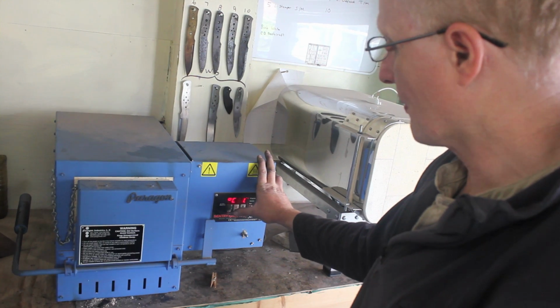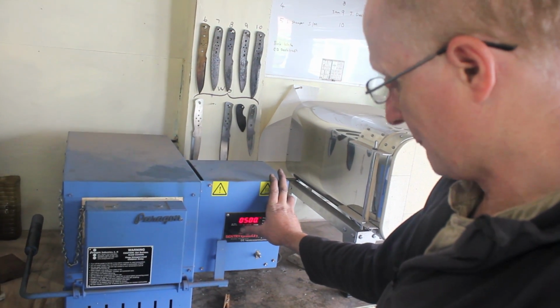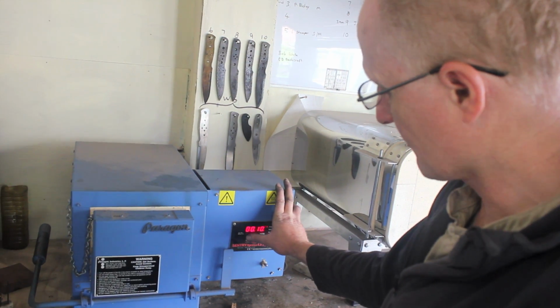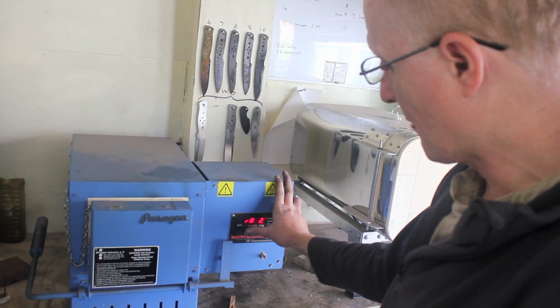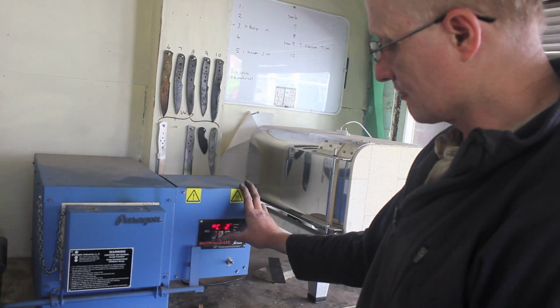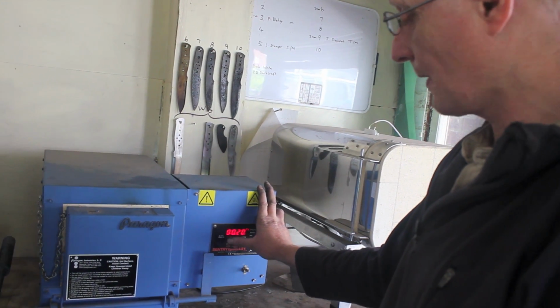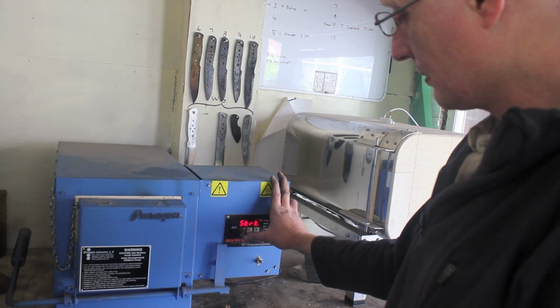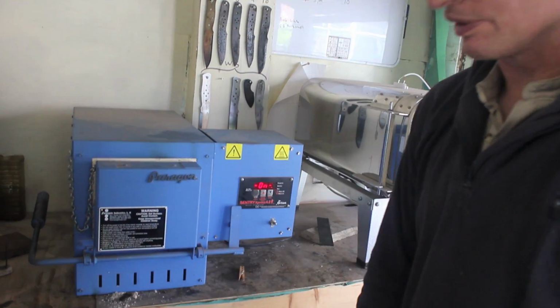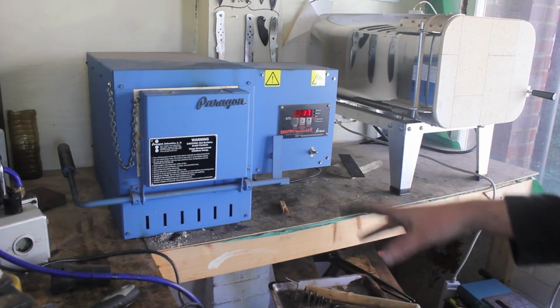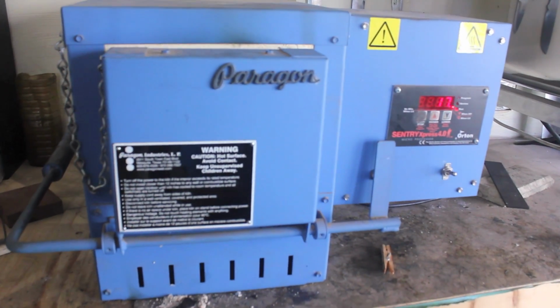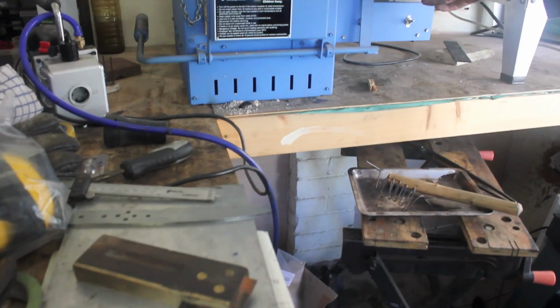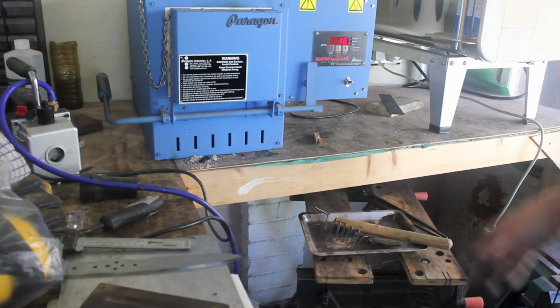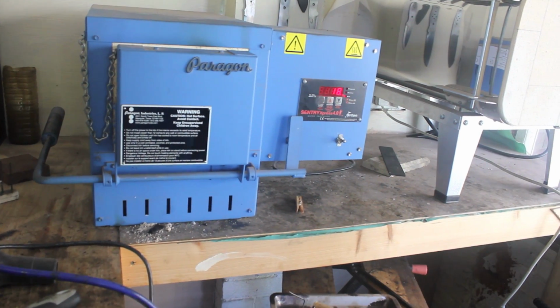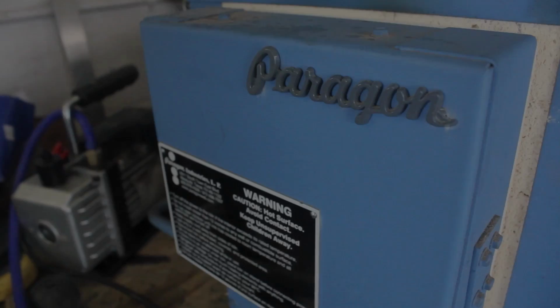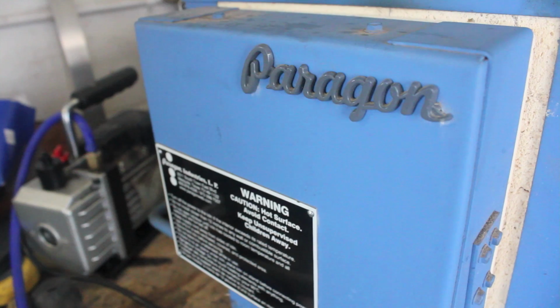It will ramp at full power to preheat the blades at 500, and it will hold at 500 for a period of time. Then it'll ramp on full power again to the final temperature, 810 centigrade, and then again I'll hold it at 810 for a period of time, and then we'll start. And the kiln now is going to run that cycle, and at the end of that cycle we'll withdraw the pieces and quench them in the vegetable oil. This temperature will start to climb in a minute. Yeah, we're up to 18, then it'll just go on and on. It takes about half hour to get to hardening temperature. And we're starting to climb again now.